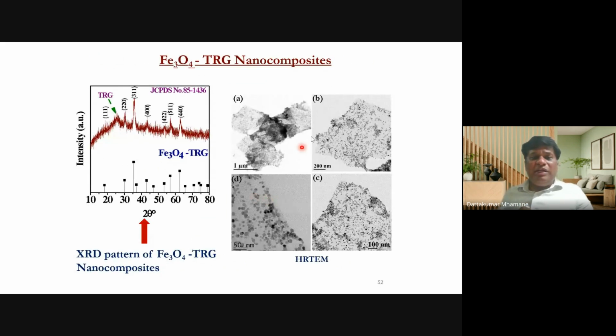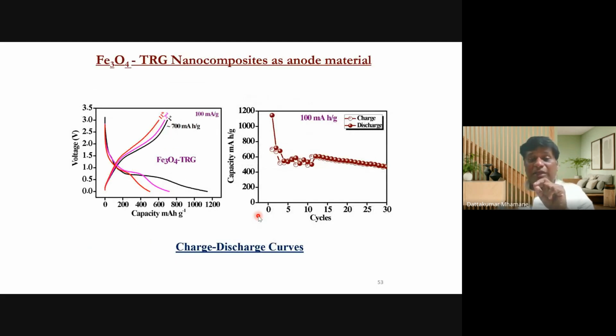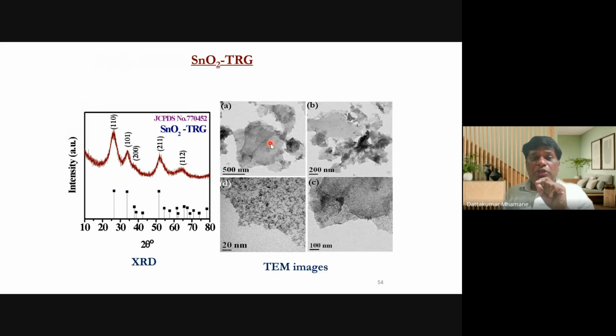I'm not going into the details, but I will show you. This is a graphene sheet, and you can see Fe3O4 nanoparticles, monodisperse Fe3O4 nanoparticles, are there, and these are the images we got. Then this is the capacity, we got around 700 to 800 milliampere hour per gram specific capacity in the case of Fe3O4 graphene.